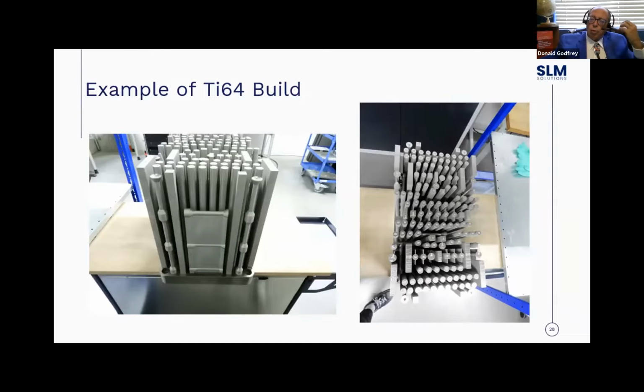of the part, because what you want to know, particularly in alloys like titanium or aluminum, is are you getting the exact same mechanical properties at the top of the build as you are at the bottom of the build, right? Because aluminum, particularly, when you have really long builds, it starts to age. And this is also true with certain stainless steels. So you may have a build here that's 4 days, right? So this part of the build down here has been exposed to 200°C build plate temperature for days, whereas the part of the build up here may be exposed to a little bit less than that for 8 hours, right?